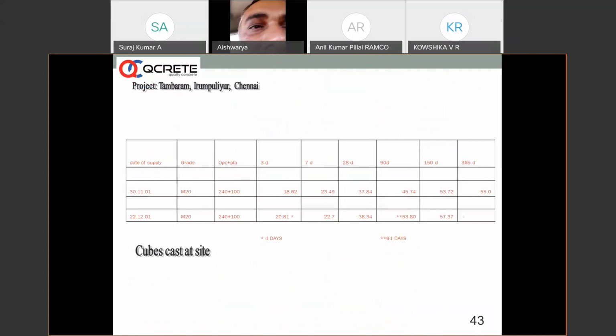The cubes were cast on a site in Chennai in 2001, and you can see here the 28-day strength is 37.84 for a 240 OPC and 100 kg PFA mix. This fly ash comes from Ennore Thermal Power Plant, and the cubes were tested for compressive strength at 365 days, and you can see 55 MPa. So the jump is from 37 to 55, almost about 20 MPa. Similarly, you can see a jump of almost 20 MPa between 28 days and 150 days for the cubes cast on site.